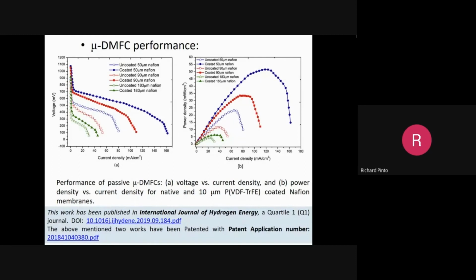Uncoated, for 183 micron, is a low power density. You know why? Internal resistance is high. So it is not very useful, but people use it for a long lifetime because methanol permeability is low. At the same time, methanol permeability is high for this 90 micron thick one. That's why you've got a low power here and a high power here with coating.